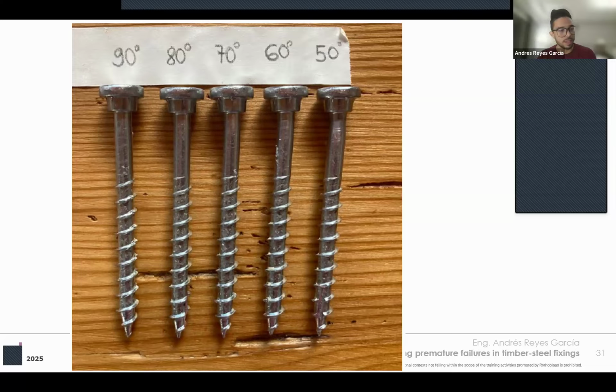It has been demonstrated, and this is a thing that needs to be researched, that hydrogen from manufacturing tends to diffuse into the atmosphere, at ambient temperature, let's say. Stored fasteners are liberating hydrogen right after they are finished in the manufacturing process. So generally, and that's the case, for example, for Rothoblaas screws, from production to selling, generally months pass in stored conditions, and this is becoming the state of the art of knowledge about hydrogen embrittlement. The most likely case is that in that time hydrogen has diffused into the environment, so there's no more internal hydrogen. So if we take this into consideration, then the moisture problem remains, and it's definitely the most